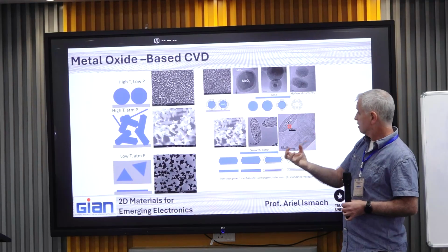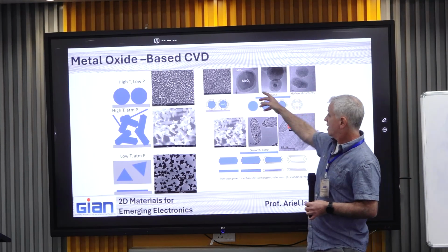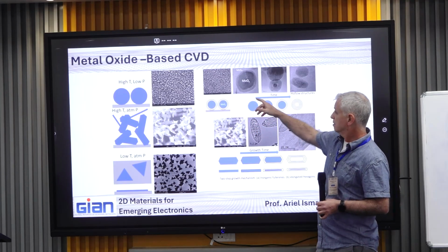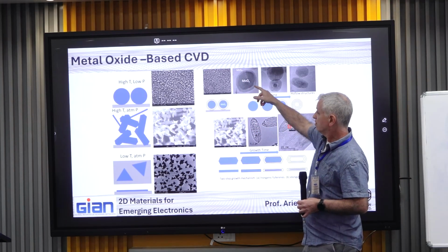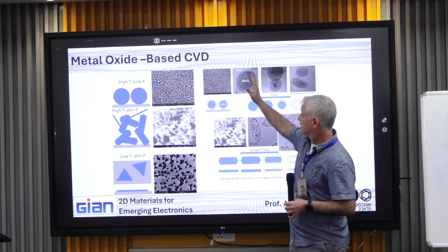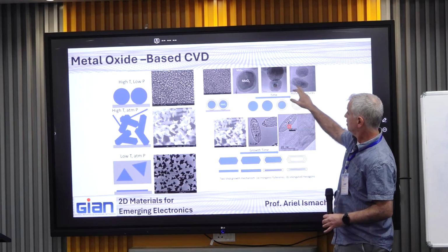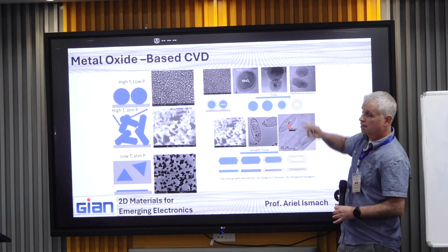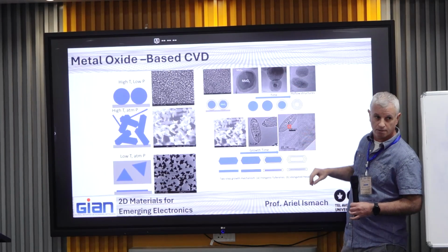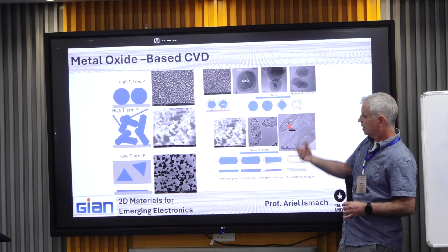They are not entirely spherical, but they are particles, and they are formed in a totally different way than the carbon ones. In this case, you first need a nanoparticle of metal oxide, and when you sulfurize it, the sulfurization starts from the edges and moves inwards until all the metal oxide has reacted, and you end up with a hollow inorganic fullerene. This is how it looks. It's similar to C60, but a different structure, and usually multi-layered.